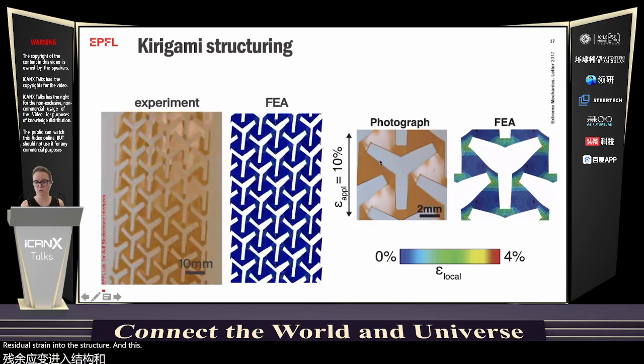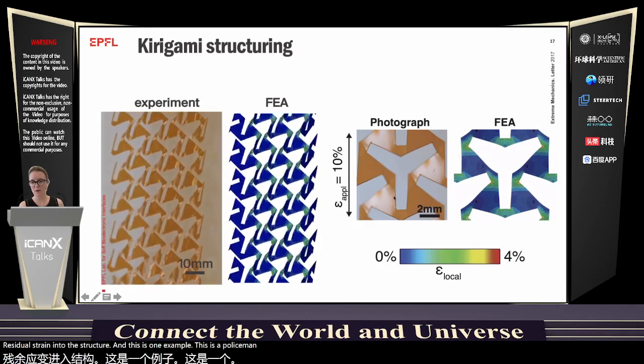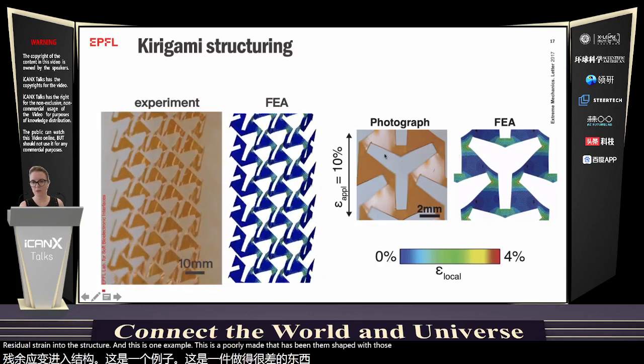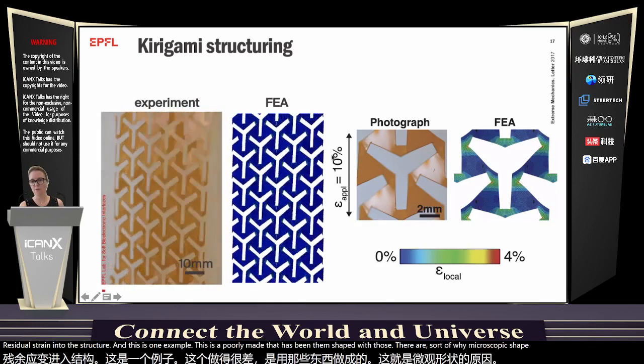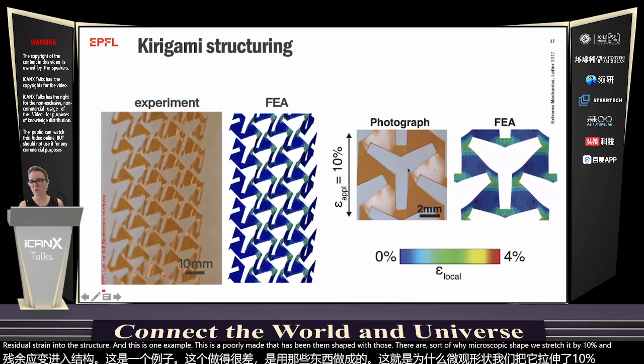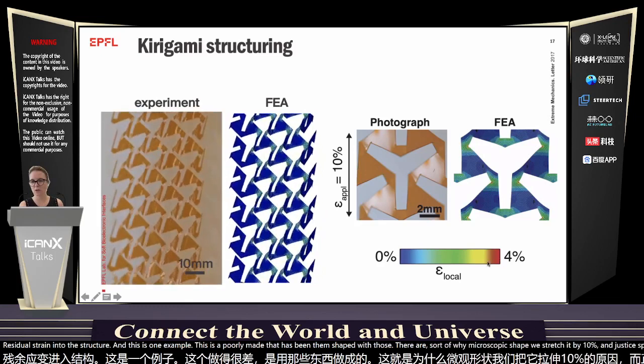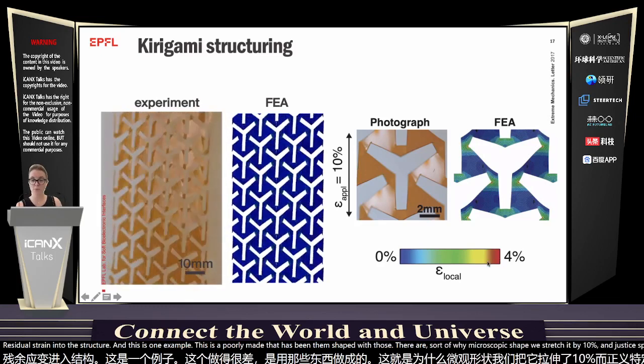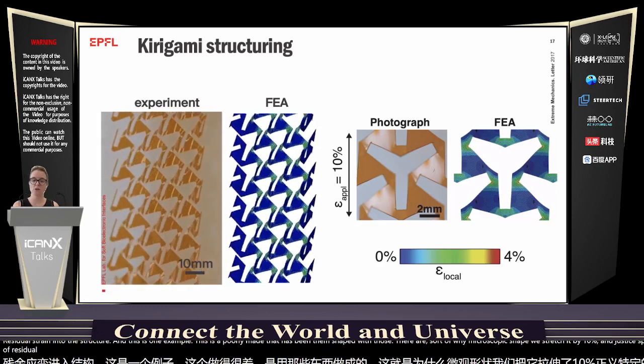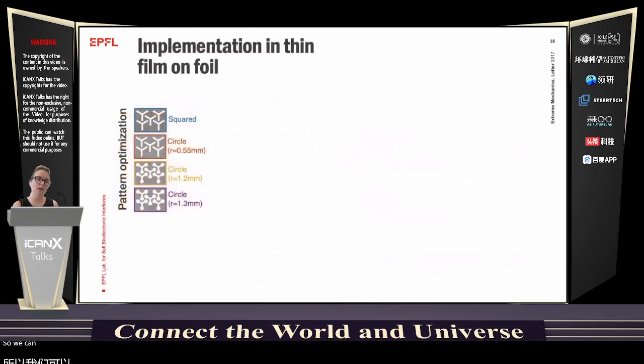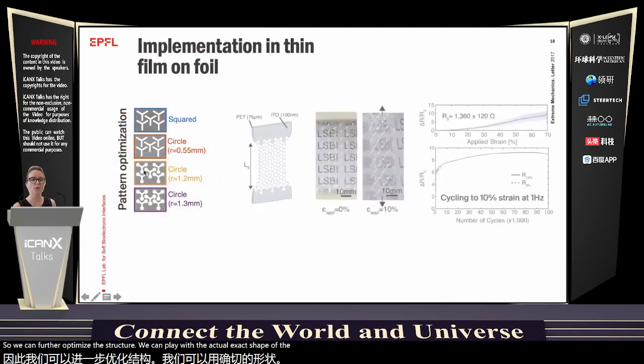And this is one example. This is a polyimide that has been shaped with those sort of Y macroscopic shapes. We stretch it by 10%, and just this specific geometry allows us to go no higher than 4% in terms of residual elongation in the structure. So we can further optimize the structure. We can play with the actual exact shape of the pattern we're replicating.